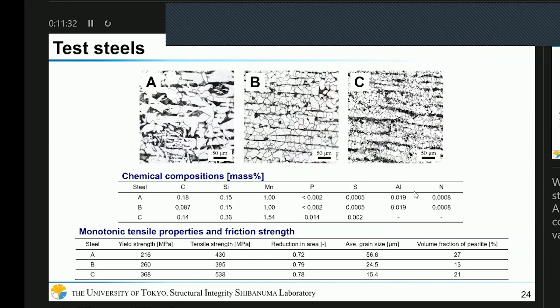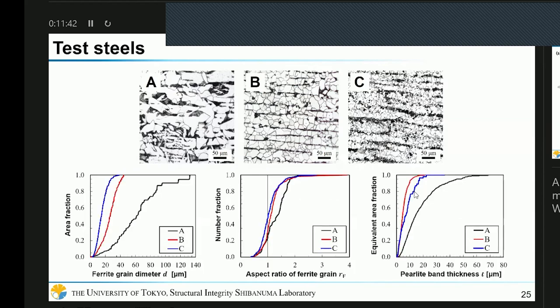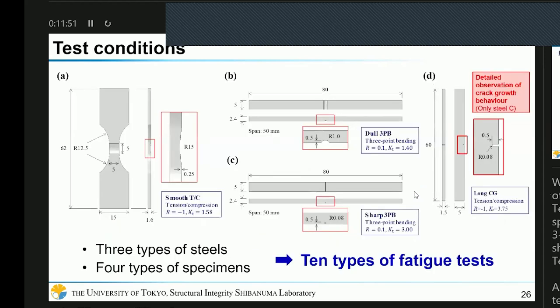So we employ three kinds of steel. We can see a wide range of variation in the chemical composition, strengths, and grain sizes. And this is the information on the size distribution of the microstructures. We use this information as the input data. And we perform fatigue tests using these four specimens: a smooth tension-compression test, a 3-point bending test with a blunt notch specimen and a sharp notch specimen, and a fatigue test to observe crack behavior. So we employ 3 types of steel and 4 types of specimen. In total, we perform 10 types of fatigue test.